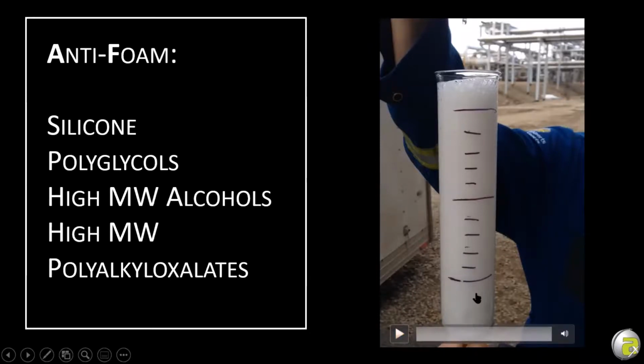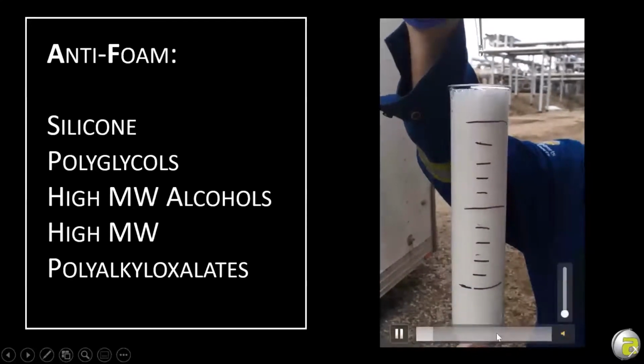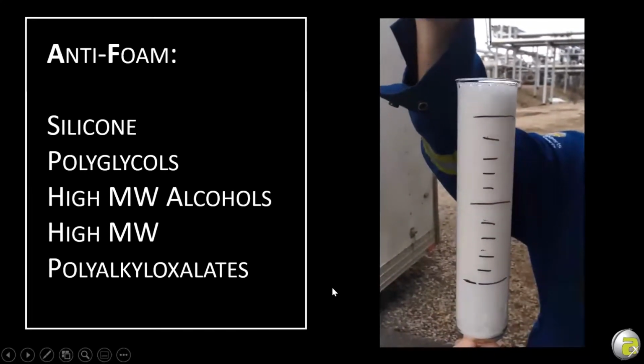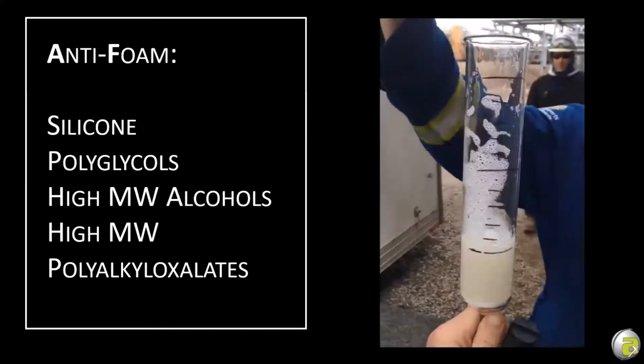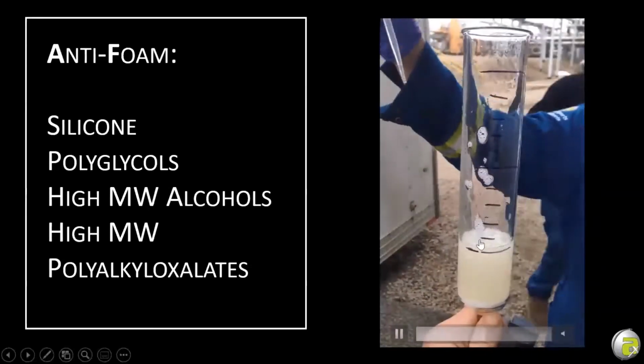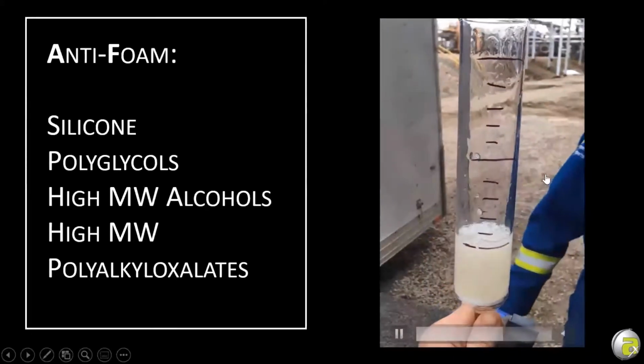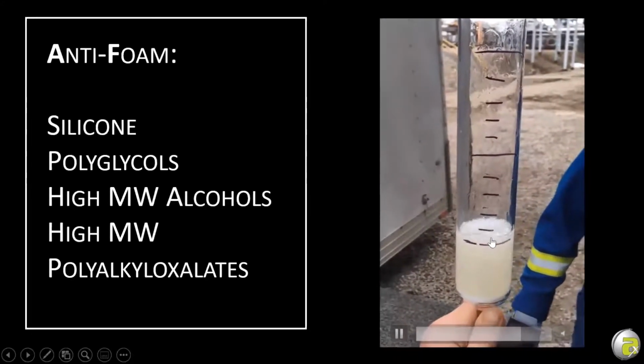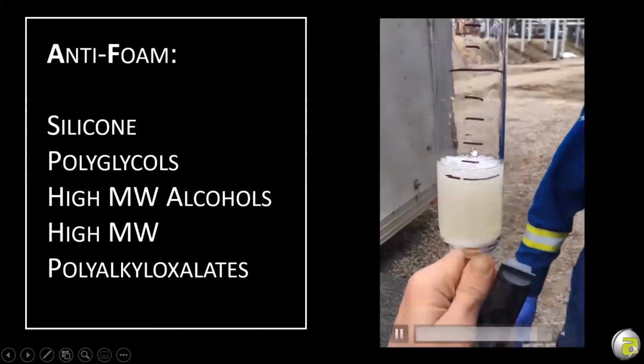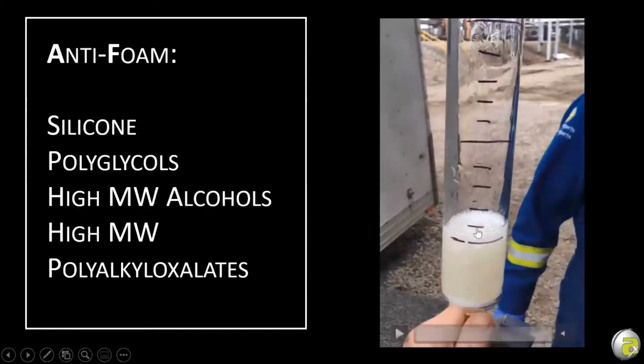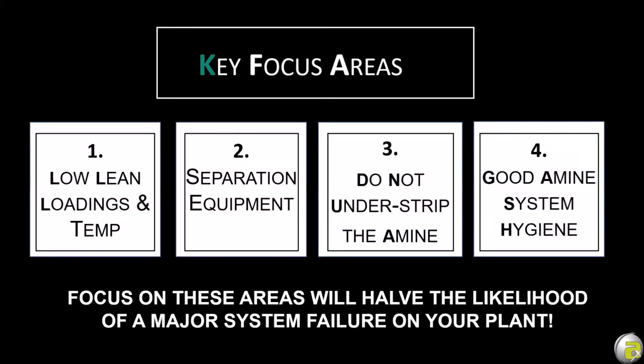So we've got quite a foam inside this particular facility. And we're going to drop some anti-foam in there. Probably could have done with just 2 drops, but bang, down to nothing. And that guy was in witness protection, so he didn't really want to be in the video. But this is what we expect to see from an anti-foam injection. Not only does it immediately kill the foam, but the foam doesn't return. If this doesn't happen in your plant, you don't have the right anti-foam for your facility. And that's something that you can check and test to get you the proper anti-foam.